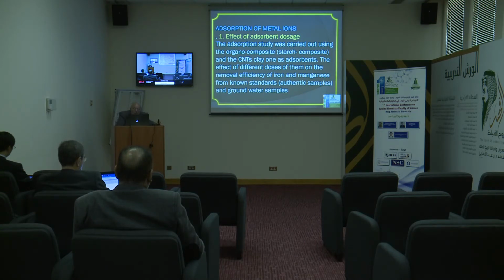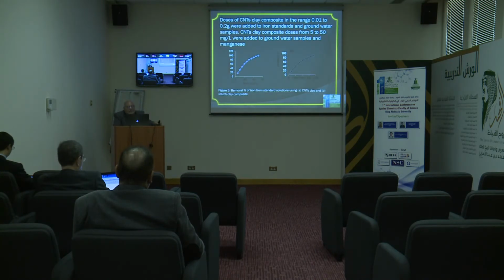First of all, the effect of adsorbent dosage. The adsorption study was carried out using the organocomposite, the starch composite, and the carbon nanotubes clay one as adsorbents. The effect of different doses of them on the removal efficiency of iron and manganese from standard solutions and the authentic groundwater samples was studied, and it was then applied directly on the real samples, which are groundwater samples.